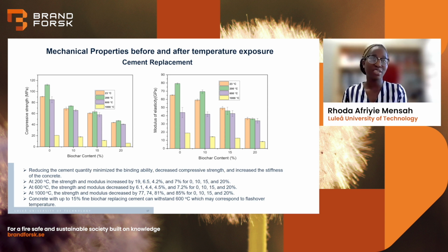But if we look at the two figures, we see that with 15% fine biochar in the concrete, the results were not statistically different from the 10% and 0%. And even at 600 degrees Celsius, there's no significant decrease in the strength. So we can conclude from this slide that even with up to 15% fine biochar in cement, it can withstand 600 degrees Celsius, which also corresponds to flashover temperature in building fires or structural fires.